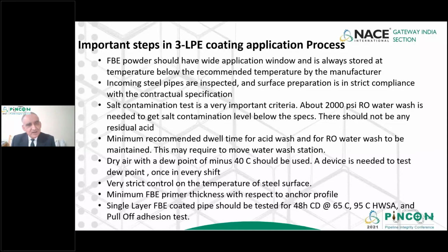First of all, select the FBE powder which has got a wider window, so that it can take care of the fluctuations in the conveyor speed or fluctuations in the pipe temperature. If the FBE powder does not have a wide window, and for any reason the temperature fluctuates, then the adhesion levels may vary. So that's very important.